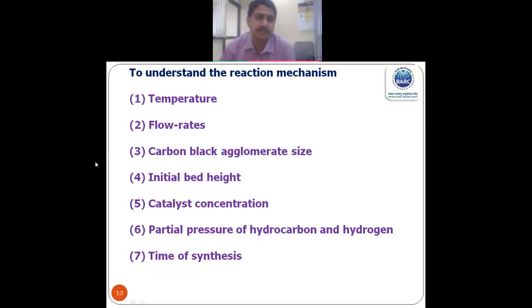Now we studied temperature, flow rates, carbon black agglomerate size, initial bed height, catalyst concentration, partial pressures, and time of synthesis. Why so many parameters? Each has its importance. First is temperature. If we do the temperature study, we can find out the activation energy. If we plot the Arrhenius equation, 1/T versus ln of rate, then we get the activation energy,